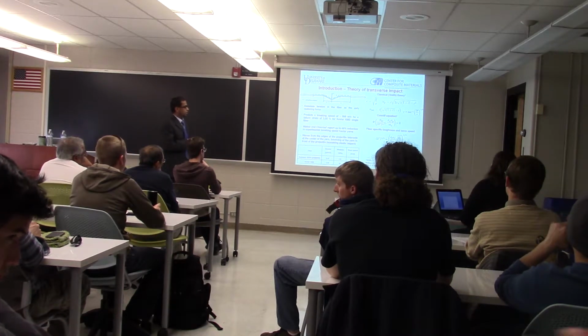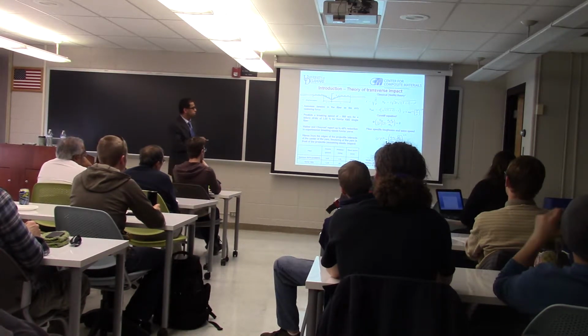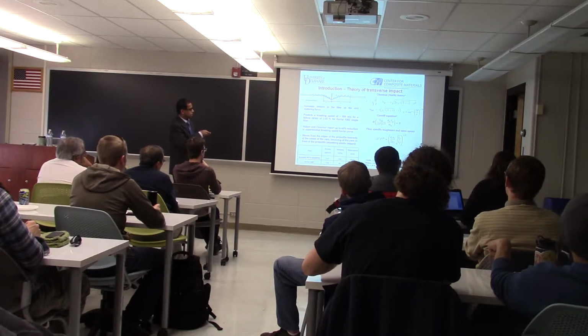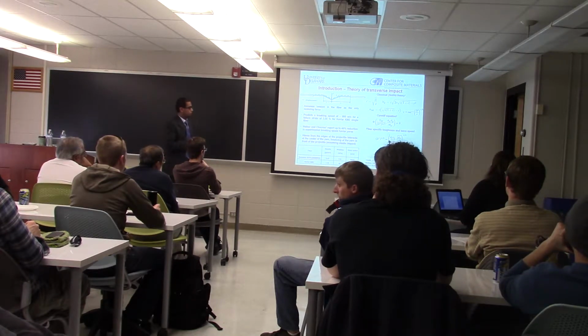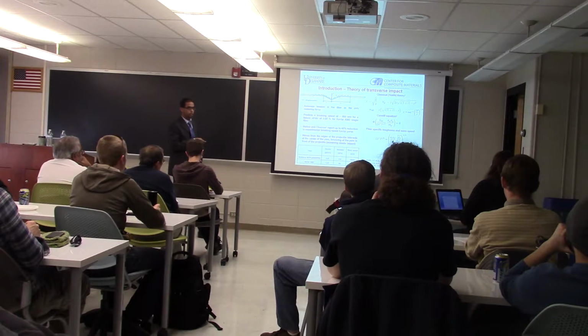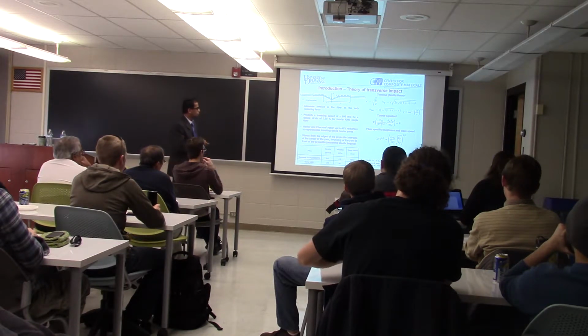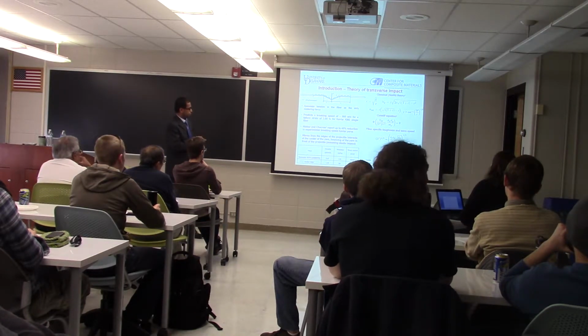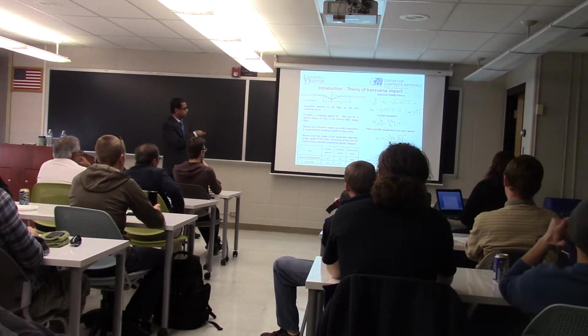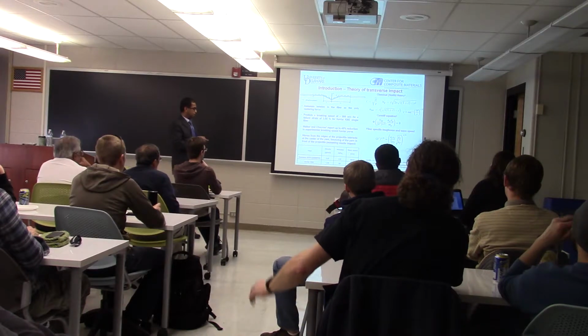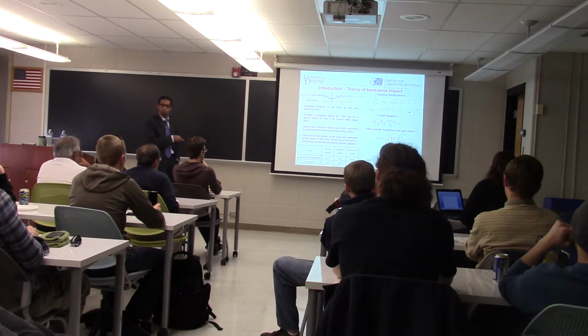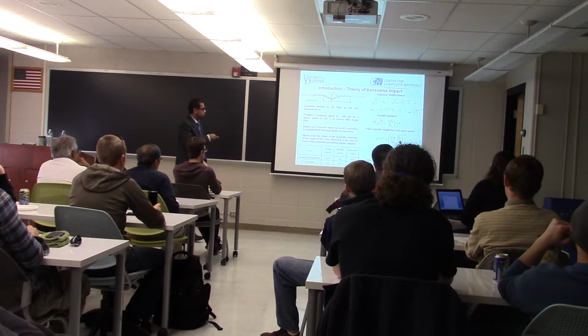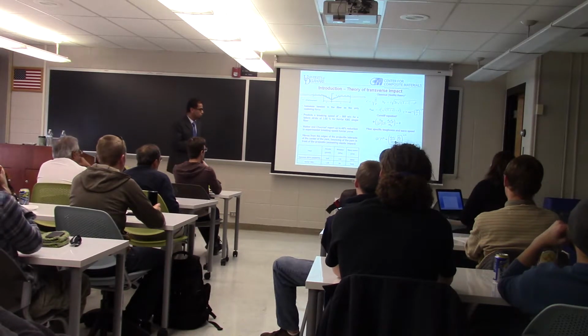So this theory correlates well with experiments in terms of both wave speeds and the angle that the transverse wave makes with the horizontal. But there is some discrepancy in terms of predicting failure. For example, these Kevlar fibers have a failure strain in the range of 3.5%. For this failure strain, the theory predicts a breaking velocity, that is the velocity required to rupture this fiber, around 850 meters per second. Whereas experimentally, folks from Southwest Research report about 40% reduction compared to this theoretical prediction.